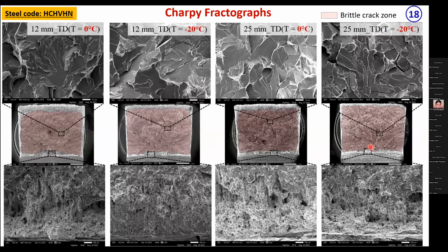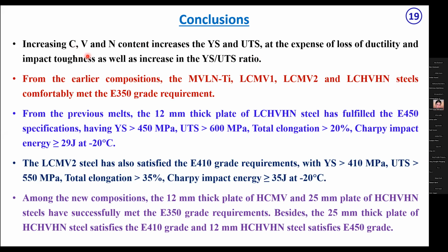So this is the conclusion: naturally it is expected that increasing these elements will improve the properties. In some of these grades, we exceeded the 350 requirement. In the 12 mm thick plate of low carbon grade, we fulfilled the 450 requirement with very exceptional properties. In this grade, we exceeded the 410 requirement. And even this time, with high carbon, high vanadium, we satisfactorily meet the 410 grade for the 25 mm plate and the 450 grade for the 12 mm plate.